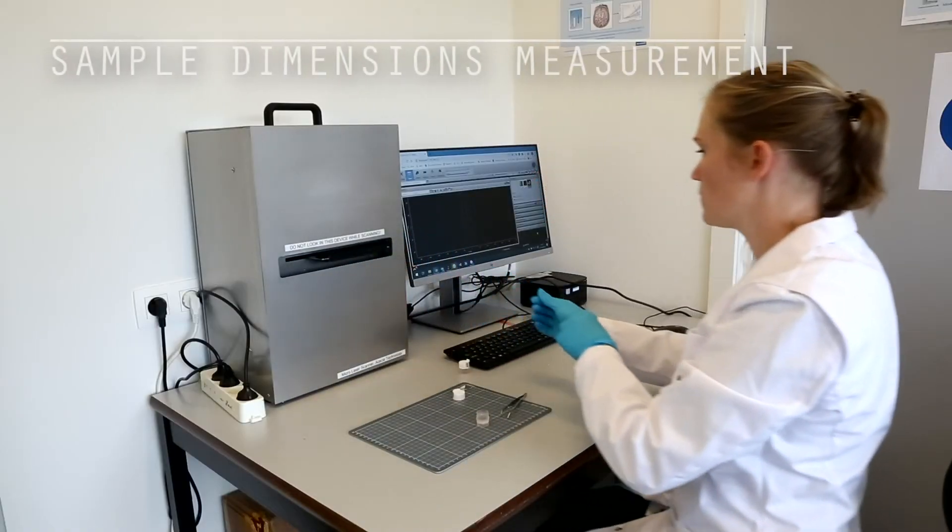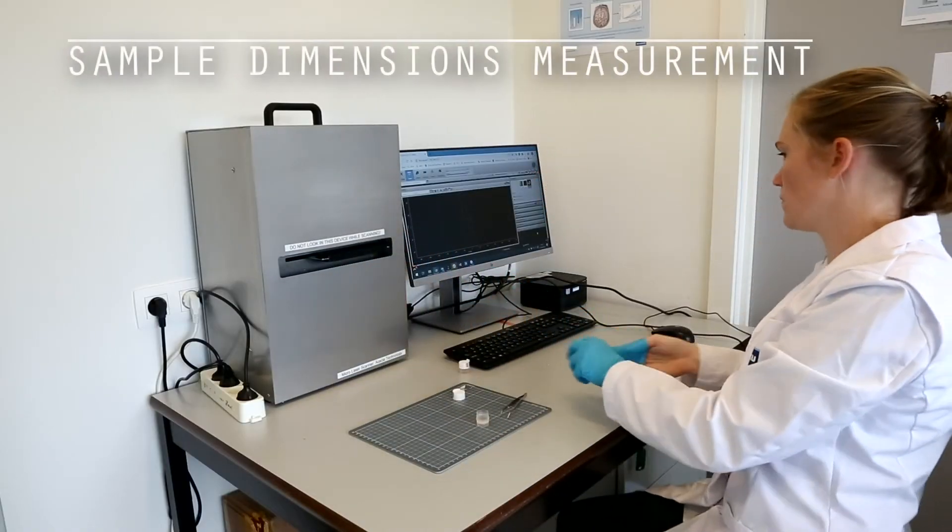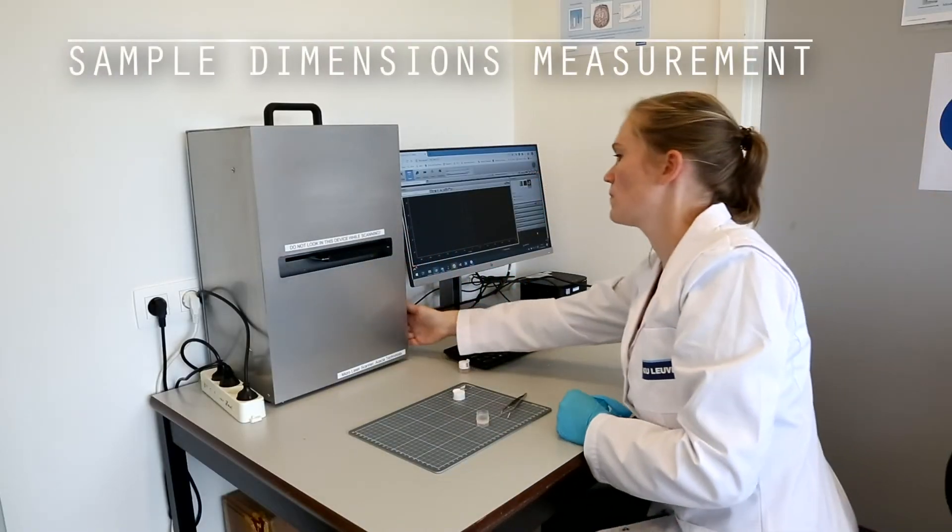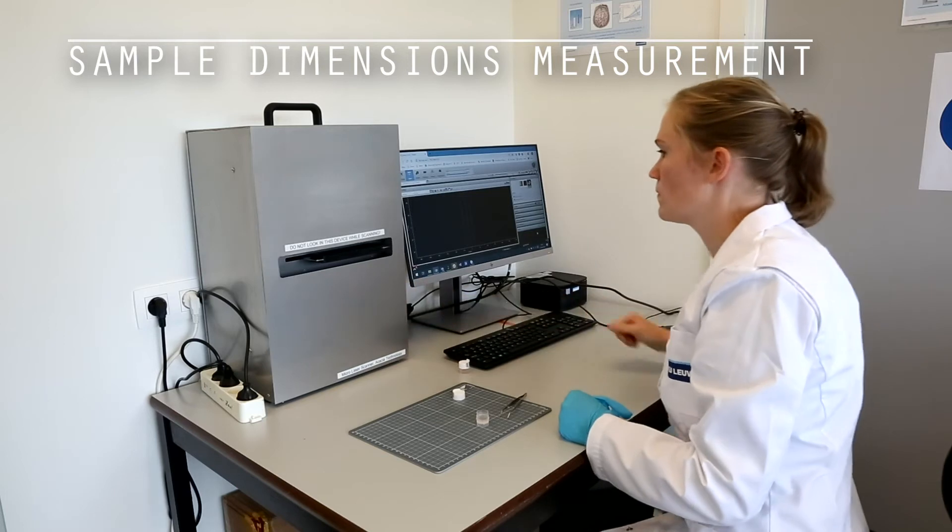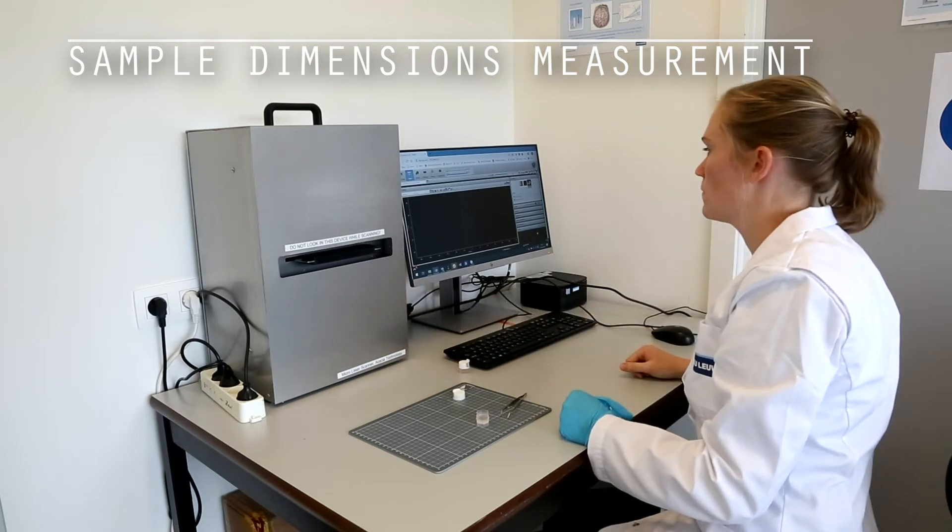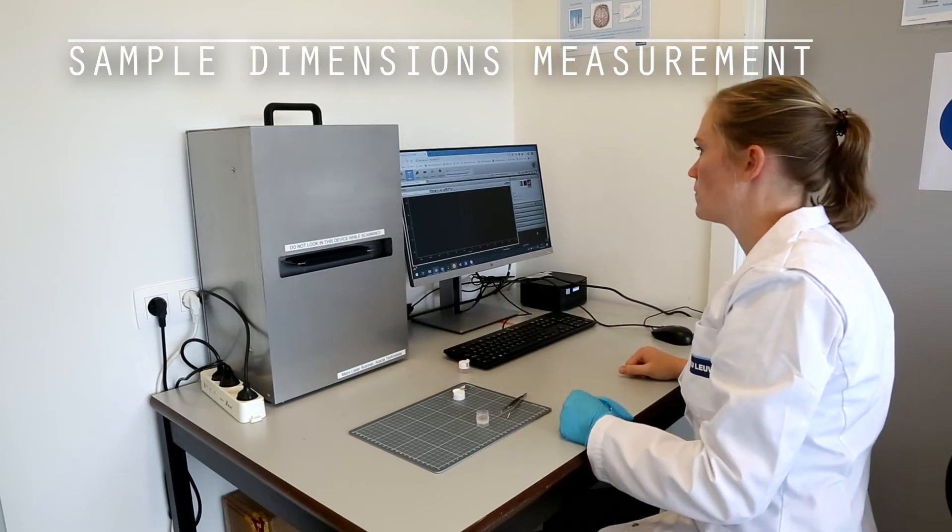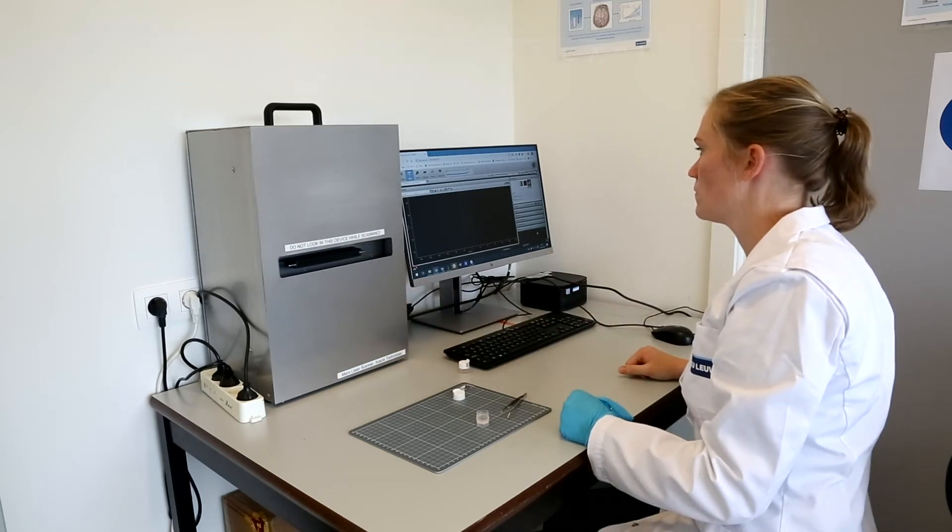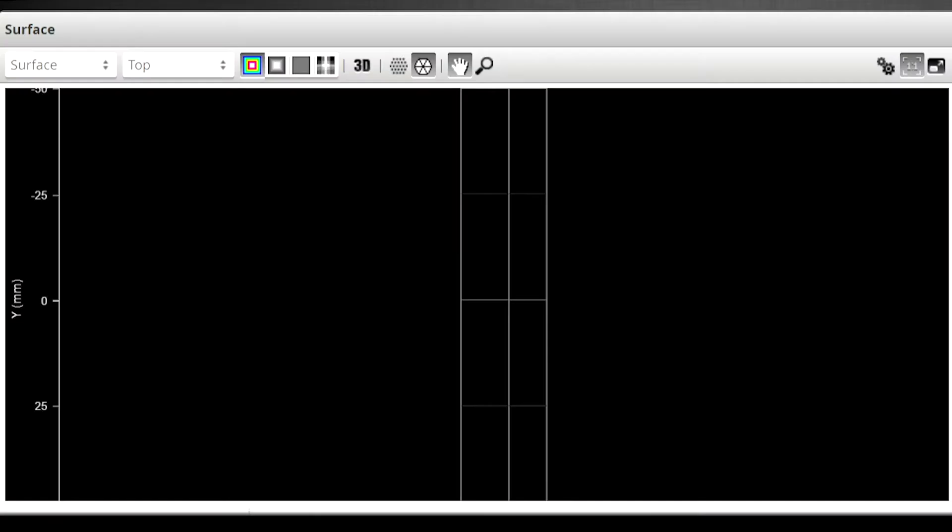Then, the dimensions of the sample are measured with a micro-laser scanner using the principle of laser triangulation. The output data is a point cloud of the sample showing the contour and a thickness map.